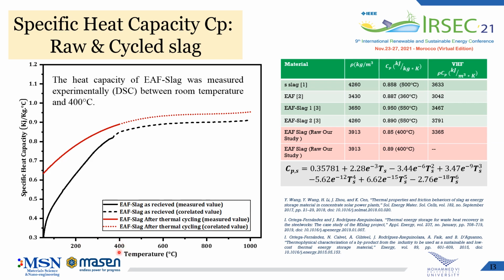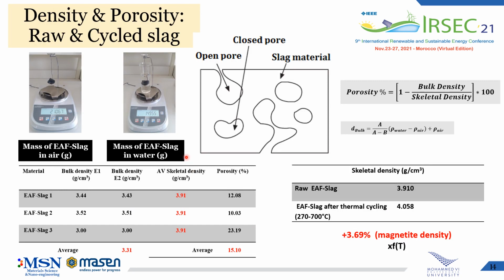For high temperature, we have measured the bulk density and skeletal density using Archimedes method and the helium pycnometer method. We found a value of 3.3 grams per centimeter cube for the bulk density and 3.9 for the skeletal density. Then the porosity was calculated using the following equation. We found a value of 15%. After the thermal cycling, the skeletal density increases, and that's due to the magnetite density being higher than the